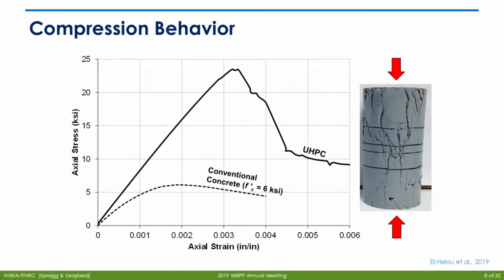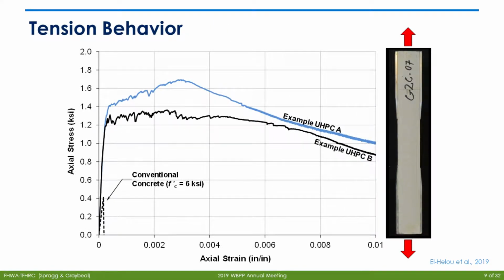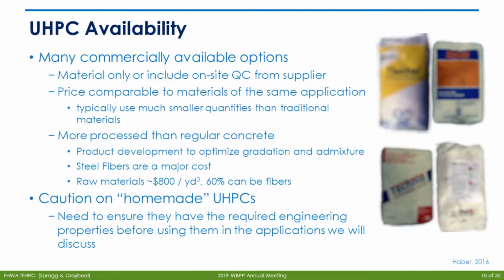Compression behavior is very similar to normal concrete, except maybe a little bit higher. The real special part of UHPC is its sustained tensile behavior. So you're able to reach at least 700 PSI, and also it's able to sustain that over a larger amount of strain. UHPC is available from a lot of different manufacturers.